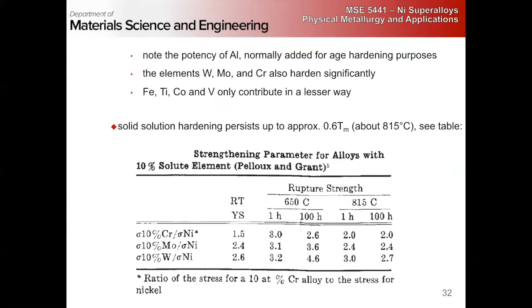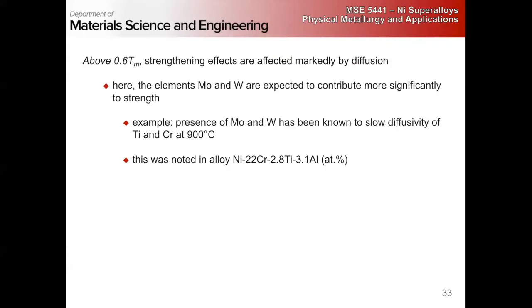So you can be between the gamma prime particles, right? And generally, these measurements aren't done on blade alloys where you have 80% gamma prime, right? These will be done on lower strength, lower gamma prime fraction alloys. Right. Once we get above 0.6, we have diffusion to consider, as well as the thermal activation of dislocations, right?